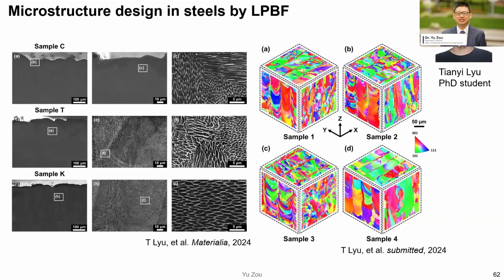And also we can use additive manufacturing method to control and design the microstructure. This project was done on stainless steel, where we can control the printing parameters and optimize the grain orientation and the texture.